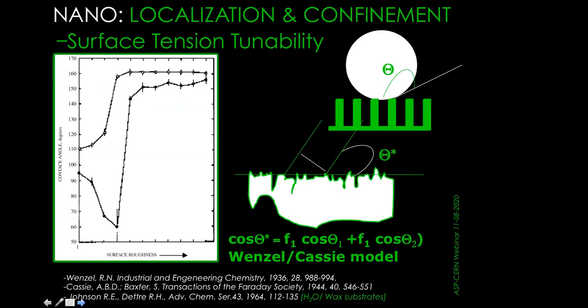This was a basic model of what we call the model of Wenzel and Cassie that was published just before the Second World War in 1936, and just after the Second World War in 1944, whereby it was demonstrated that if you have a rough surface, you will be able to control the contact angle. And this is the contact angle which controls the surface tension. Then they showed that indeed, if the roughness is small, the contact angle is small, and when the system is rough, the contact angle increases.